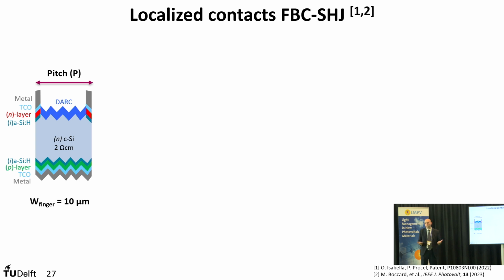The problem is that you cannot get any charge carriers out of your device if you don't passivate it well. And one way to passivate it is to make sure that, at the really atomistic level, you remove all those silicon atoms that have been displaced by the reactive ion etching. So we typically can do some kind of TMAH-based defect removal etching that allows us to get back good passivation, but then you lose the anti-reflectivity because everything becomes a little bit more rounded. And then, it's always a trade-off, unfortunately.